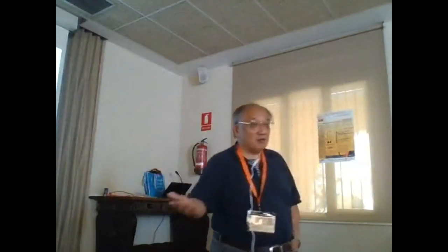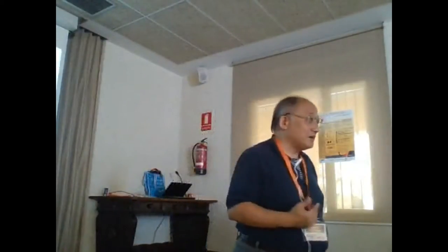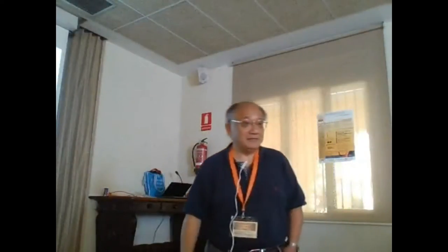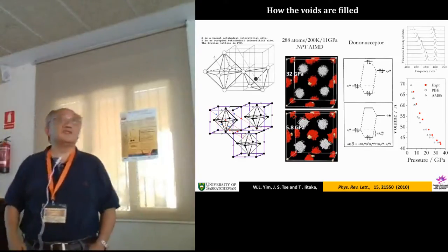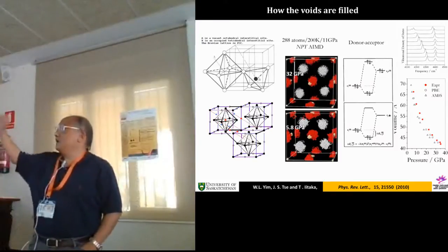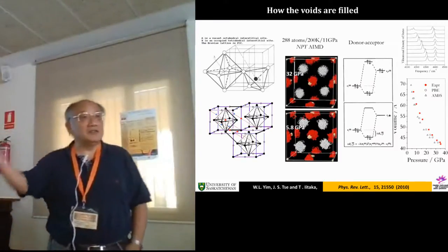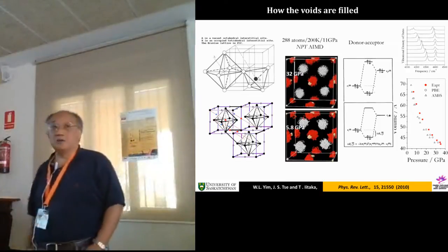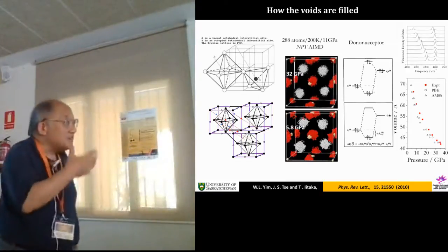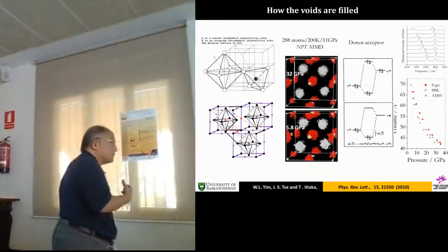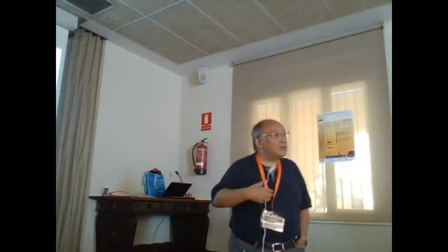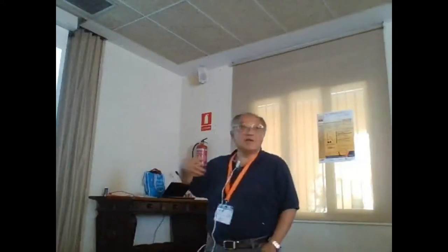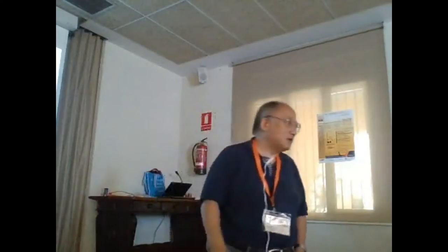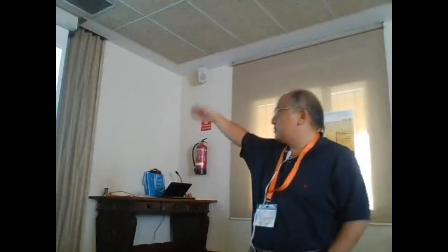In fact, for calcium at 40 GPa, we measured that the thermal expansion coefficient is one order bigger than in normal calcium, all right? The bonding here is fairly simple, actually. It's just a dative bonding of the electron donating from the hydrogen into the lower-lying d orbital of silane. So in a sense, it is very exciting to form this kind of closed-shell interaction compound. But at this pressure range, the normal chemistry concepts still work fairly well, and you can quantify it by doing calculations and matching the experiment. I don't want to go into it.